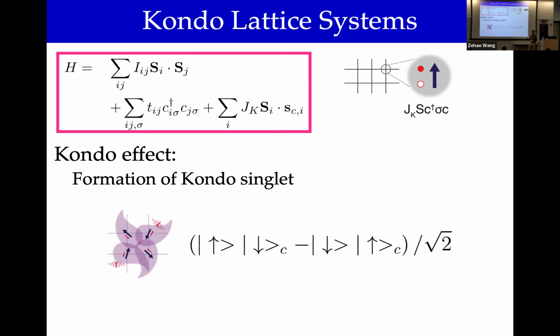You can consider this as a model, but it's also good to keep in mind that these spins are nothing else but the original f electrons, which have their own dispersion E_k and their own Coulomb interaction U. It's just that the f orbitals are hiding inside some extended orbitals, screening is small, the effective e squared over r is larger, and the hopping is weak, so the Coulomb interaction is large compared to the bandwidth.